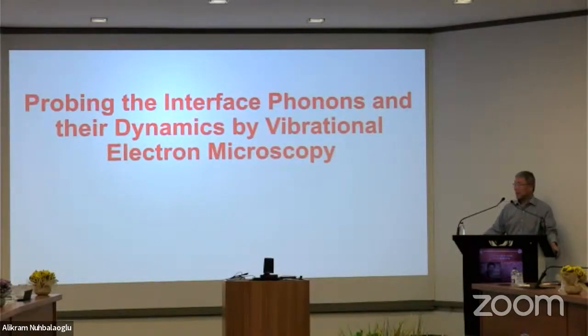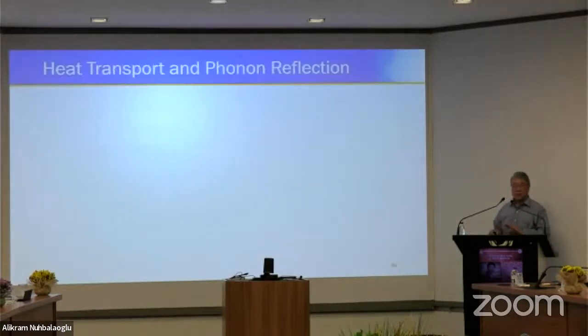But if I have 5 more minutes, I'll touch on another area I planned to talk about. With advancements in electron microscopy, both the aberration corrector and the monochromator, plus the direct electron detector, today we can have high spectral resolution. We can have a very small probe for the scanning transmission electron microscope. And we can also build improved energy analyzers to analyze small energy changes in the electron beam. So we use electron energy loss spectroscopy. With this, we can study the dynamics of lattice vibrations, or phonons, for individual defects, which was not possible before.